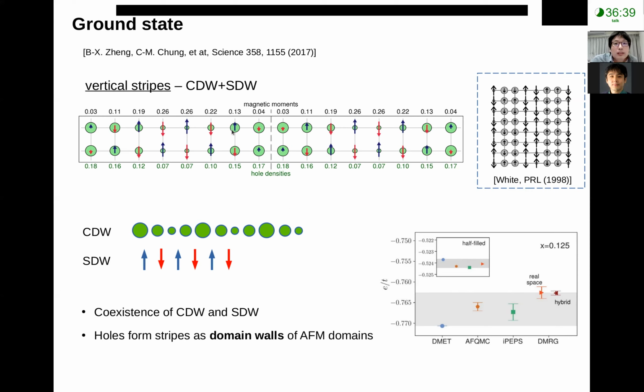But also these two orders are coexisting in an interesting way, where you see the hole concentrate in a specific position, and the holes go in one of the directions. So if you copy this unit cell to a 2D plane, you see the holes split into several lines that we call stripes, like going here or there.